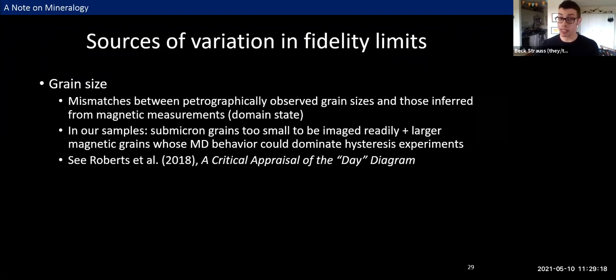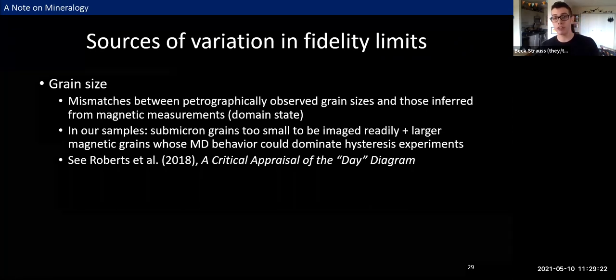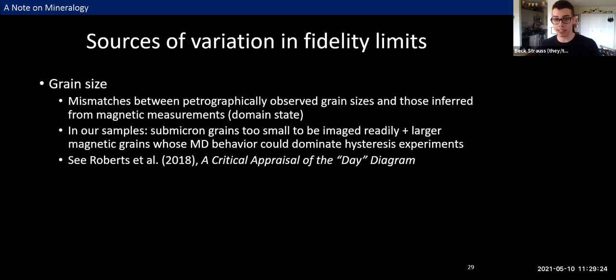Okay, so we've talked a bit about grain size, and long story short, we see some interesting mismatches between petrographically observed grain sizes and those that are often inferred from magnetic measurements by way of domain states. And in our sample specifically, we observe two different populations of iron nickel grains that we wouldn't have been able to differentiate from hysteresis experiments alone.